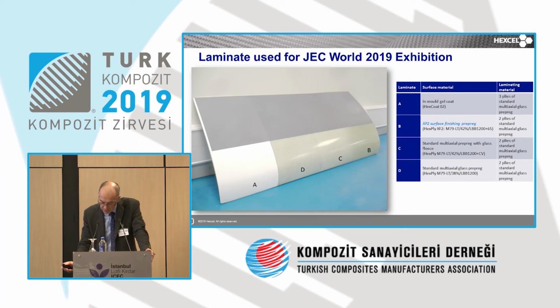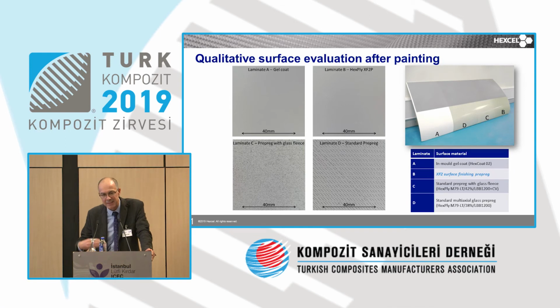We presented some parts there to illustrate the difference between the current technology using a gel coat and this one. And as you'll see, there is no real difference at the end of the day. The aspects are very, very comparable. The only interest, I would say, is that because there are not that many steps, you end up saving up to 30 or 40% takt time in the overall process, which can make a big difference when you're making many hulls.